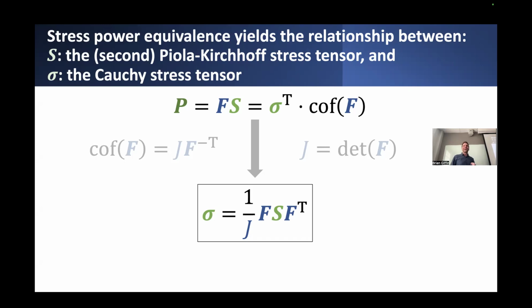It required a little bit of a digression. It required thinking about things and almost diving into thermodynamic principles in order to come up with this expression, but it's fully consistent. It's energetically consistent, sometimes called thermodynamically consistent. It's a consistent representation of how those two different measures of stress should be related to one another. And it also involves, I'll just define here for convenience, J, which is nothing more than the determinant of the deformation gradient. Oftentimes you'll see that as a commonly used symbol, but in any case, it's just the second Piola-Kirchhoff stress, left and right multiplied by F and F transpose.